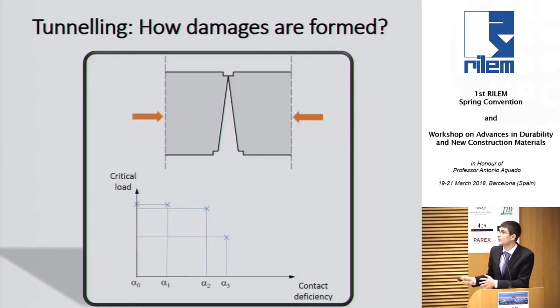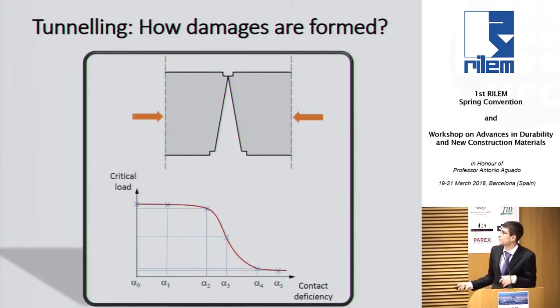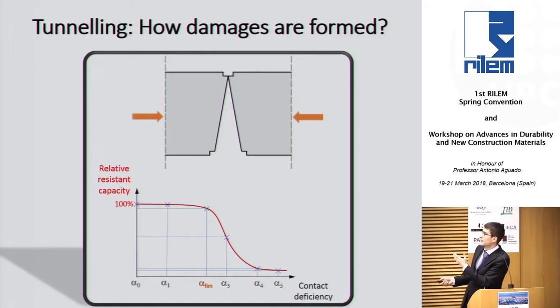If you increase it a little bit more, you're going to see a trend, right? You might see these types of trends here. So there's clearly a limit value above which the capacity of the segment is reduced significantly. So the first step of the research was to identify how this happened, or where exactly this limit is for typical tunnels, right?